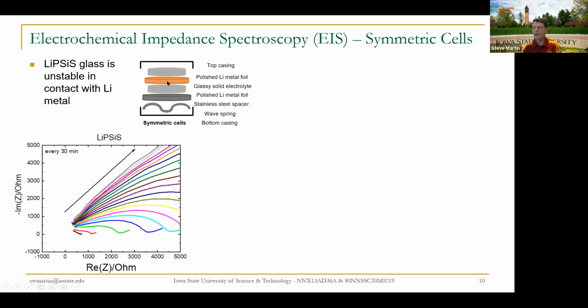That's a really strong test of the chemical stability of the electrolyte. We take a glassy electrolyte here, a tablet of the glass, and we sandwich it between two pieces of lithium metal. Lithium metal, of course, is really reactive, which is why we use it as a battery material. What we don't want to happen is shown here. The glass immediately reacts with the lithium and forms impedance. You can see this is impedance.